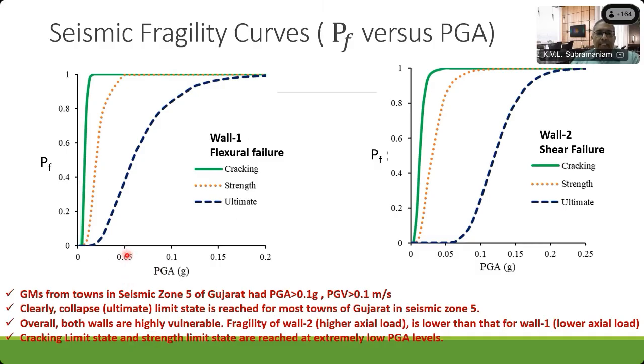If you look at something like PGA of 0.05 G, you'd find that about 40% of the walls would have failed. They would basically have no capacity left in them. Now, by the time we come to a value of 0.2 G, which is actually quite severe, most of these walls would have failed. And the walls that would fail in flexure would essentially have failed.